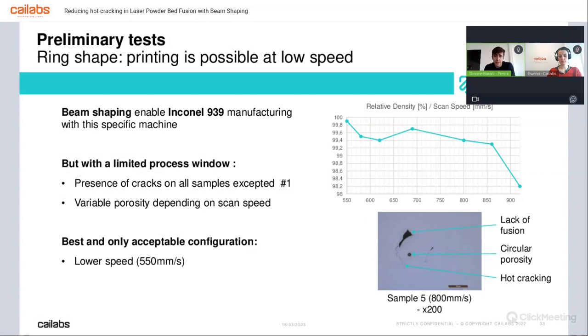layers. And then you have a circular porosity, again correlated to the fact that you don't have such a good cohesion between the part and the powder, and you can have some gases trapped inside. And then starting from one point that is critical, so the edge of the lack of fusion, a hot crack starts, basically because you have some stresses that are increased by the presence of, for the case of Inconel 939, gamma prime phases that have grown out of control, and it has created more stresses, leading to hot cracking. The only result that was really good was at the lowest scan speed, that was 550 millimeter per second, where we reach a density of 99.9% and no presence of hot cracking.